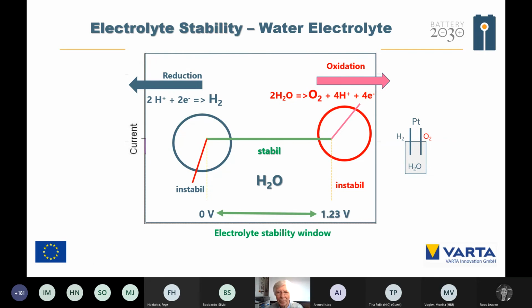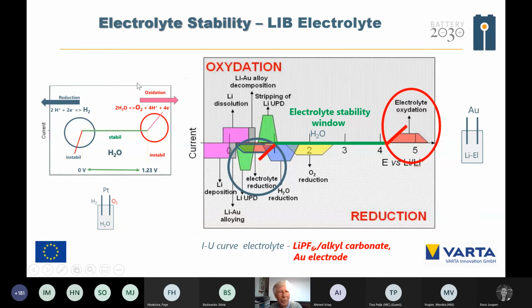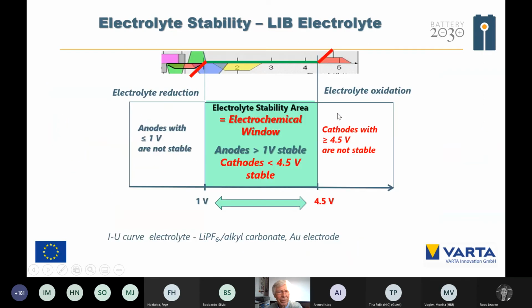That is for water, but we could take the same experiment also for our lithium electrolyte, the LiPF6 alkyl carbonate, with two gold electrodes. And we have nearly the same behavior. Going in the positive direction, the electrolyte is oxidized, and going in the negative direction, the electrolyte is reduced. Where for water we had 1.23 volts, here we have nearly a 4 volt electrolyte stability window. So we have an area of stability, the electrochemical window between 1 volt and 4.5, 4.3, 4.6 volts, depending on the electrolyte.